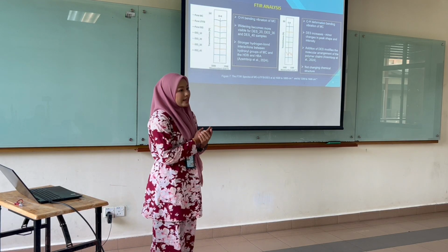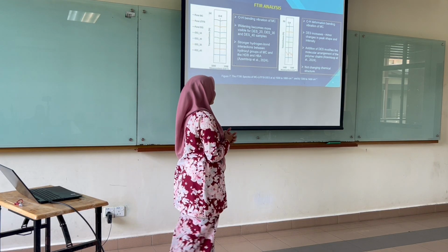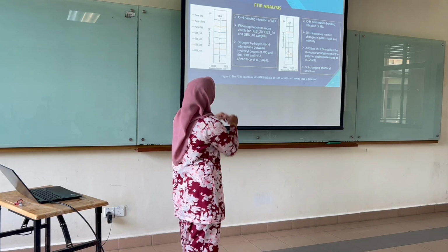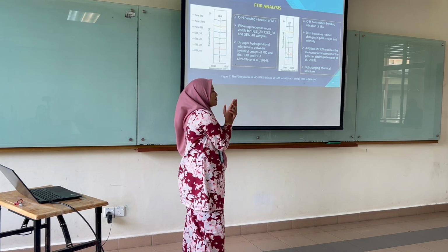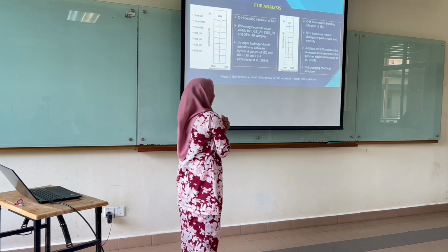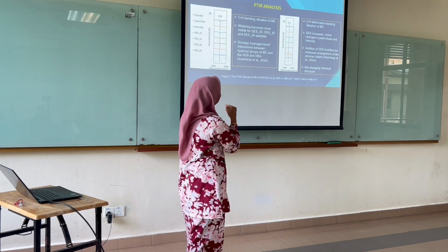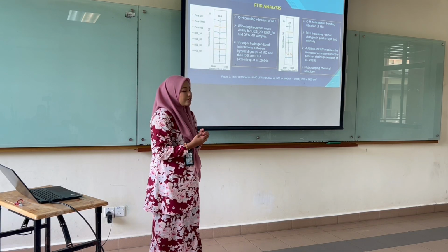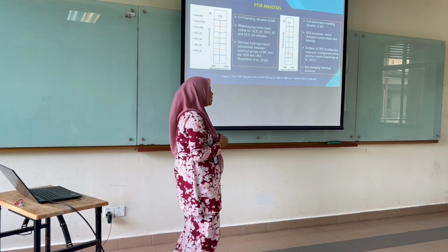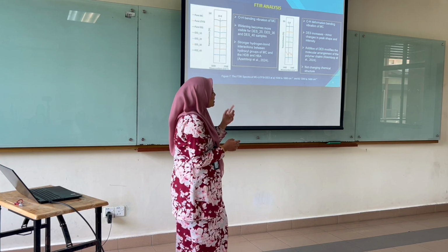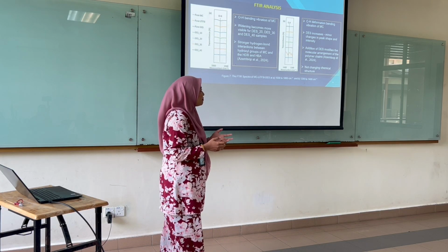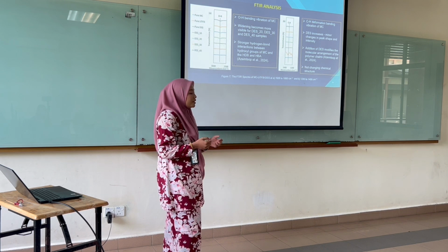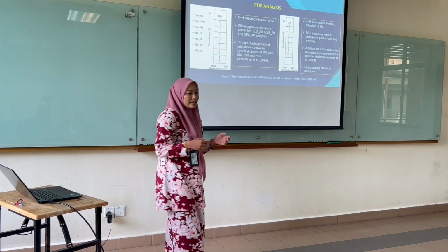Here is the result and discussion for FTIR bands. This is the FTIR spectra for the OH region and CH region. For the OH bending vibration, when DS was added at 20, 30 and 40%, the broadening becomes more visible as DS increased. This is because of the stronger hydrogen bond interaction between the hydroxyl of MC and the hydrogen bond donor and acceptor of DS. For the CH deformation bending vibration, as the DS increased, there is only minor change in peak shape and intensity seen. This is because the addition of DS modified the molecular arrangement of the polymer chain, but did not change the chemical structure.